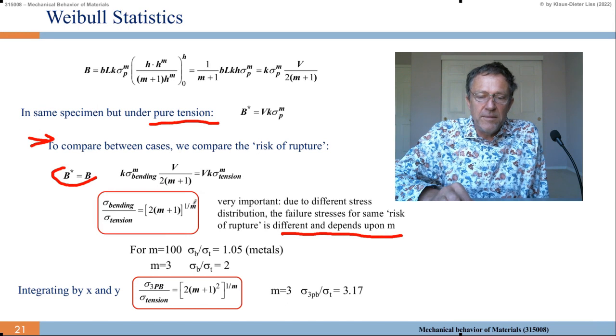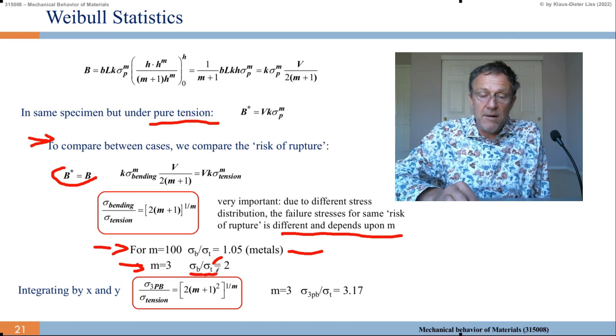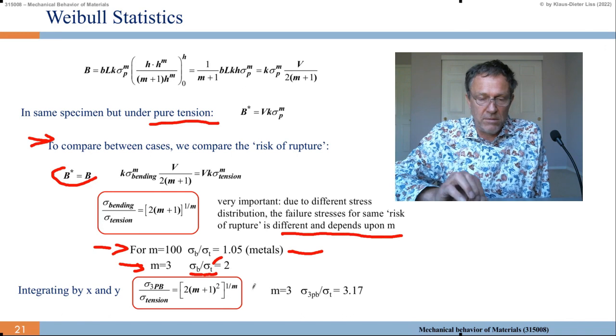If m is small, if m equals 1, let's say, then we have 2, 3, 4, then sigma bending would be 4 times as strong, or can be 4 times as high as for tension. So for m equals 100, the sigma b over sigma t is 1.05. That's what I say. If m becomes large, it goes to 1. This is for metals. And if m is 3, I just said it for 1. So if m equals 3, then sigma b over sigma t becomes 2. That means the bending stress can be twice larger than the tensile stress, or in the tensile loading experiment or situation, application in the airplane.